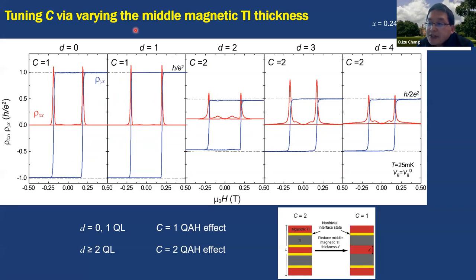In addition to the magnetic doping level, we also tune the Chern number by changing the thickness. Here, as I told you, this is a C equals 1 quantum anomalous Hall layer, and this is also a C equals 1 quantum anomalous Hall layer. We fix the doping level here at 0.24, a normal insulator layer. If we change the thickness, we change the interaction between the two quantum anomalous Hall layers. When the film is very thin, the interaction is strong, so this is still C equals 1. When D is 0 and D is 1 quintuple layer, it shows the C equals 1 quantum anomalous Hall effect, and when D is between 2 and 4, it shows the C equals 2 quantum anomalous Hall effect.